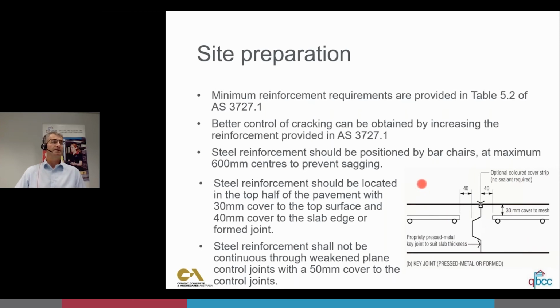It talks also about using bar chairs at maximum 600mm centers. Steel reinforcing should be in the top half of the pavement with at least 30mm cover to the surface and 40mm cover to the slab edge. And we know why that's for, right? We don't want that steel too close to the surface where it's going to be attacked quickly by moisture and chlorides. And it does say steel reinforcement shall not be continuous, but there's another diagram further on that shows where it is continuous, but it's done in a way that it's not fixed into one end.